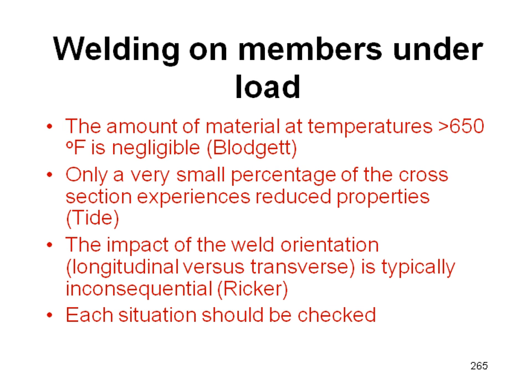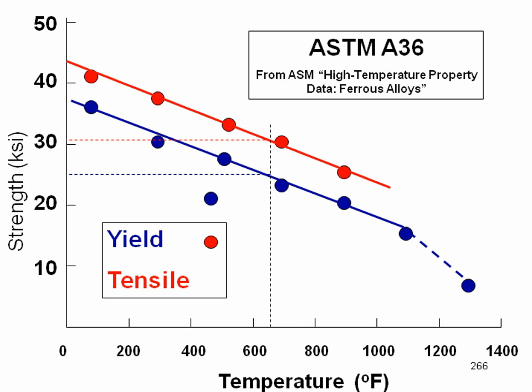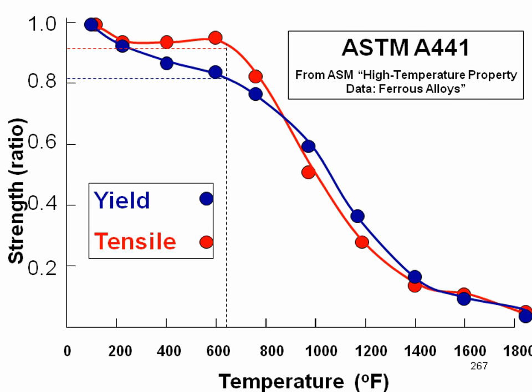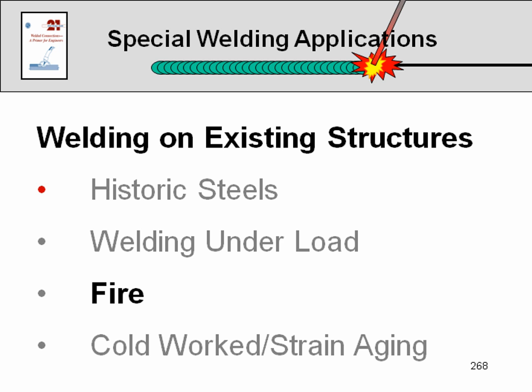Now let's take Blodgett 650. And here you see the 650 degree, and you see you still have a substantial amount of strength at that load. For the 441, it's even a little bit higher. So maybe we don't lose quite as much as we're thinking of. Another concern is that of fire. And the issue of fire is not only the combustibles in the area, but also the work leads associated with the welding arc.